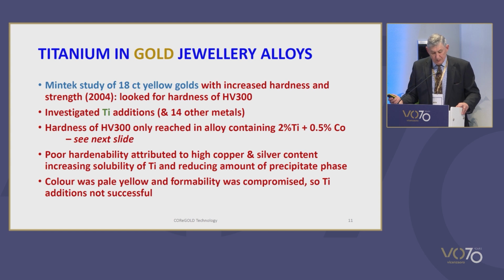The use of titanium was explored in a study of 18-carat yellow golds with increased hardness by Soos and his colleagues at Mintek in South Africa. In particular, they were seeking alloys with a hardness in excess of 300 Vickers and targeted at applications for watch cases. They explored some 15 alloying metals, including titanium, and their effect on hardenability and colour.